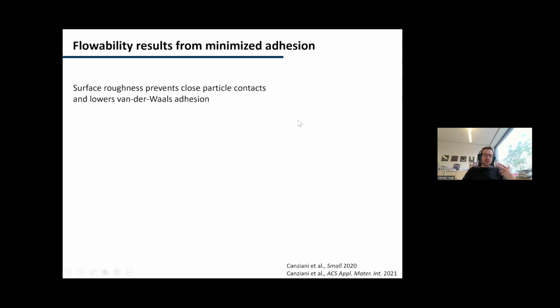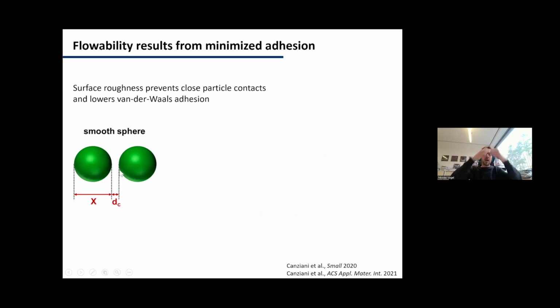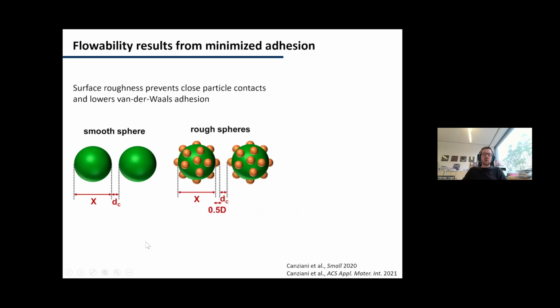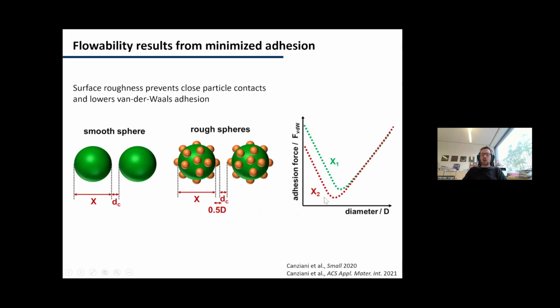in superparticles. And that is we can in situ tailor the roughness of the particles, which we can use to lower the adhesion of a powder. Why? Because two smooth spheres can come fairly close together and then start to interact via van der Waals adhesion. If we have a rough sphere, then these small roughness features prevent direct contact, and that means the particles are further apart, and that reduces the attraction.